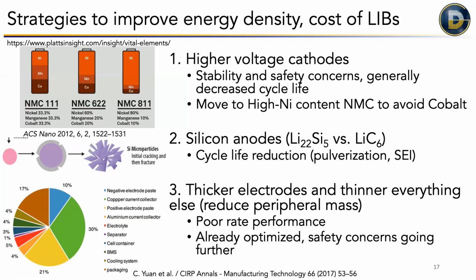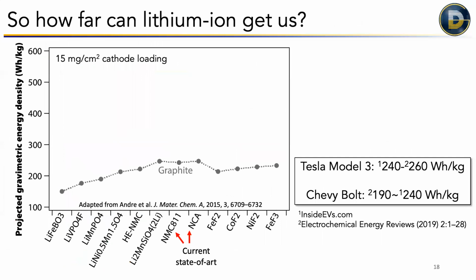Like the Samsung Galaxy Note fires were caused, in part at least, because they really tried to push the thickness of the separator down. It's only 4 microns thick, whereas the state of the art is more like 8 or 9. So it's like half, and it caused problems. So this is kind of where we're at. The Tesla Model 3 is around 250 watt hours per kilogram, depending where you look. Chevy Bolt is just a little bit behind that. That's because the Chevy Bolt uses NMC and the Tesla uses NCA. NCA is a little bit higher capacity, but has some stability issues. So Tesla's making a choice there.